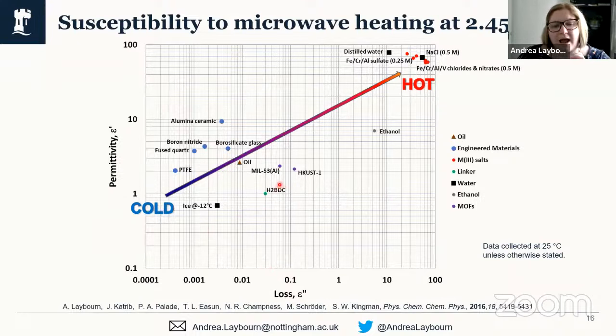So what we did was we measured a range of metal salts and a range of MOFs and linkers, and looked at their dielectric properties, and we're then looking to see how they would interact with a microwave field during the synthesis. We also benchmarked this against a range of materials that you would typically get, which are not very microwave absorbing and stay cold if you put them into a microwave reactor. And these are typically used to make the microwave reactors themselves.